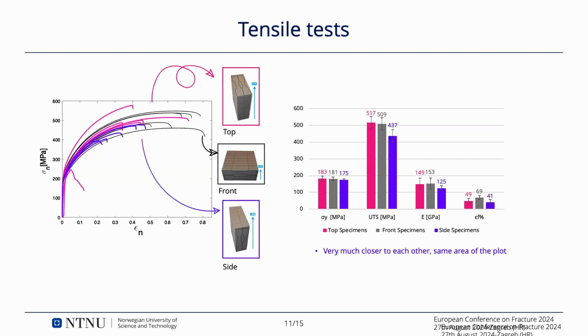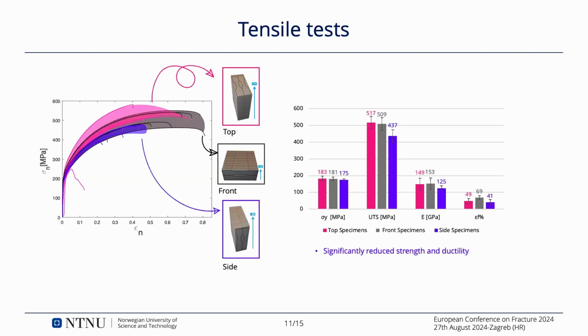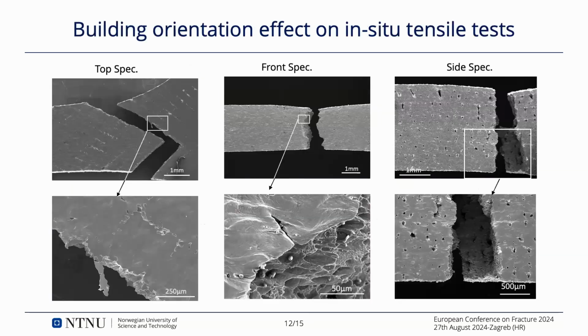And then we have the side specimens. Here I just shaded the areas to help you locate the side specimens. They are generally weaker, and they also tend to fail at an earlier stage of the test. So these are the numbers of the tensile properties, but I think it's more interesting to check the fracture mechanism. And so we performed in situ tensile tests in an SEM microscope. So we can start with the top specimens here.